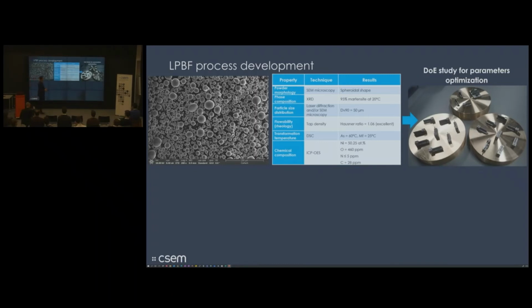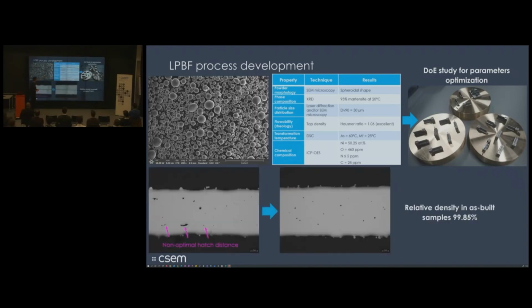So then we did the design of experiment study for parameters optimization. We usually talk about several parameters that need to be optimized in the laser powder bed fusion process. It's usually laser speed, laser power, the hatching distance, so the distance between each laser track. Then you also have a contour, which is basically the contour of the part itself, the layer thickness, etc. So we have optimized the parameters at the beginning.